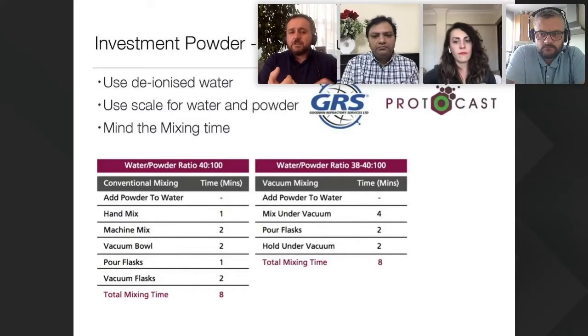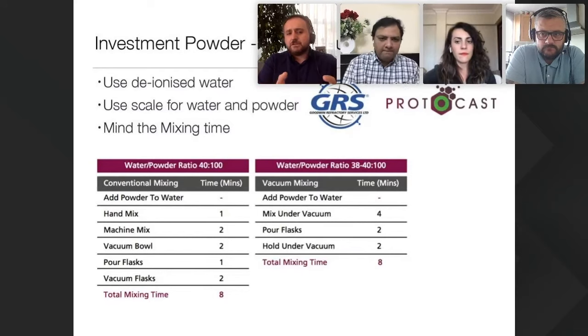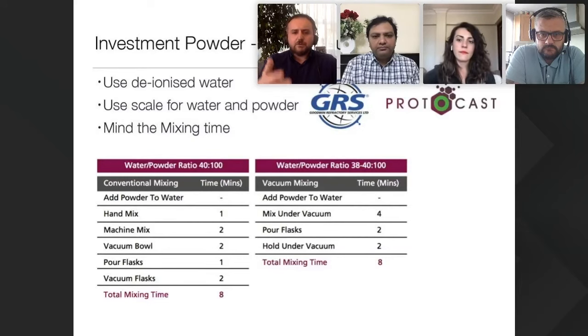What is very important, I think, is to mind the mixing time. Whether you mix with a vacuum mixer or conventional mixing, these minutes are not just there to give an idea. If you mix, let's say 2-3 minutes more or less, the chemistry will be different, so the whole process will be changed.